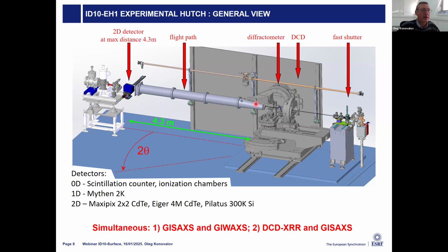And then we have a diffractometer with a detector arm, which can hold several detector schemes at the same time. And then we can measure, as I showed previously, different types of measurements like reflectivity, GISAXS, GIWAXS, and fluorescence almost simultaneously on the same sample, which is very useful to get a complex characterization of the system under study. So then we can also install the long flight tube and work up to 4 meters from the sample to detect and do high resolution for almost submicron size particles organized, or to have better resolution in real space for the system.